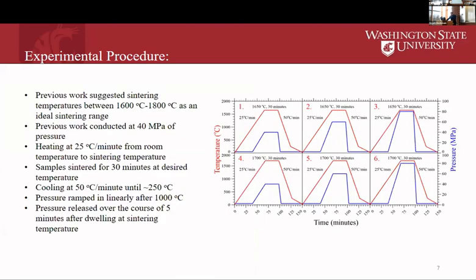On previous work we've done, we found that sintering of yttrium oxide worked best for us between 1600 and 1800 degrees Celsius, so we knew that was the target region we wanted to work in. We'd also sintered all of our previous samples at 40 megapascals of uniaxial pressure.